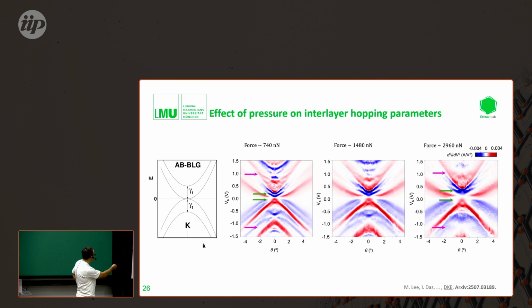So now I can just showcase here the AB bilayer measurements. In AB bilayer graphene, there are 4 bands. The 2 higher energy bands are separated exactly by gamma 1. This is the interlayer tunneling parameter between the top and bottom layer. And this gamma 1 parameter really just sets the separation between the top and bottom bands. But of course, because it's the interlayer tunneling parameter, if we squeeze the layers between the two materials, we actually enhance this tunneling, or hopping, parameter, and we can push these bands to higher energies. And this is something you can see here.